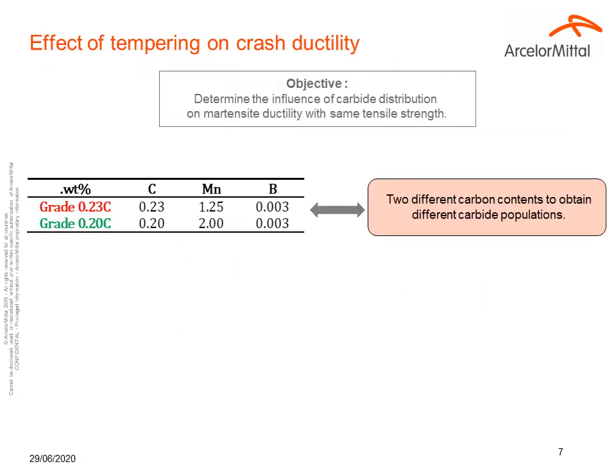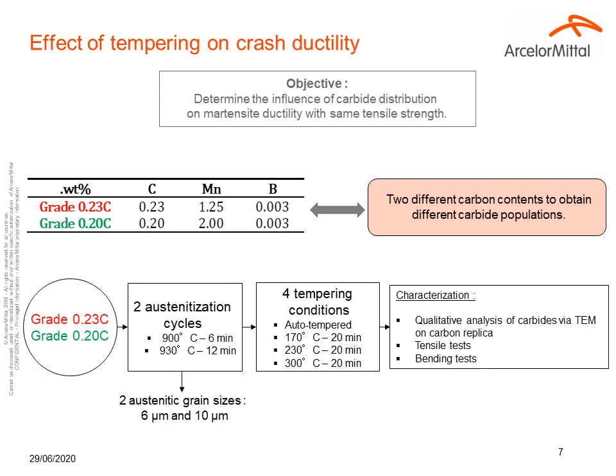The first study is about the effect of tempering on crash ductility, where the main objective is to determine the influence of carbide distribution on martensite ductility for an equivalent tensile strength. We use steel with two different chemical compositions, where the main variation is in the carbon content, as well as different thermal treatments to obtain different carbide populations. We practice two austenitization cycles to obtain two austenite grain sizes, and there are four different tempering conditions from auto-tempered to 300 degrees Celsius during 20 minutes.